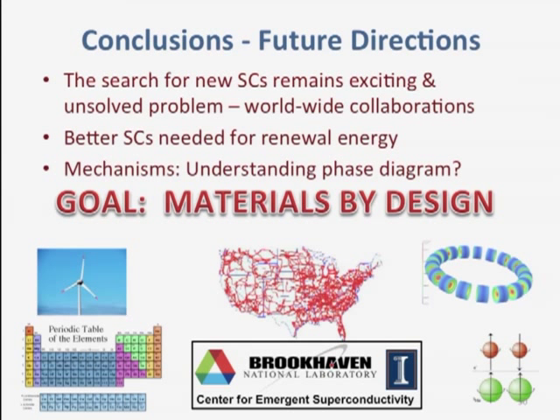Yeah. But, for example, Warren Pickett has a nice idea that by getting a material where different parts of the band structure couple strongly to different phonons, as is the case, for example, in magnesium diboride that you mentioned. If you could repeat this through different parts of the Fermi surface, coupling to many different phonons, you could get a very high superconductor. So that's a nice idea. The question is, how do you realize that? How do you make the connection between the model that you were looking at for the interactions, so electrons, and the chemistry that goes together to form the material in the first place?